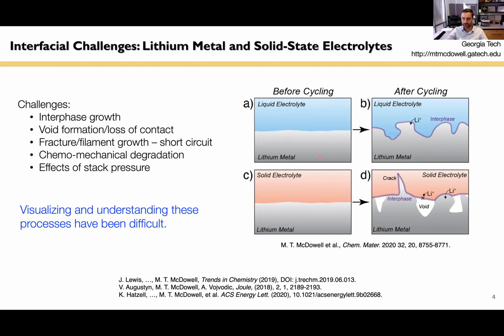So over here on the right, let me just show you a schematic explanation of some of these issues. On the top here, we have a lithium metal electrode in contact with a liquid electrolyte. This is like in a conventional battery system with a liquid. If we charge and discharge this battery, the lithium metal electrode will change its morphology. That's shown here. You can see that we've changed the shape of this thing. And we've also grown an interphase, this purple region, which is a formation of a surface film. The nice thing about a liquid electrolyte is that even though we've changed the shape and the chemistry of this interface, the liquid still contacts the lithium metal. This illustrates the properties of a liquid: there's no shear stress that can be supported, and it's flowable into electrode porosity.